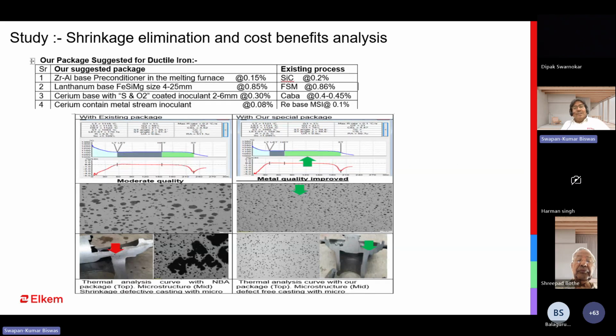This is also another study. On the left side, you can see that with the existing combination they are getting a lot of shrinkage. Then we recommended a high performing package. We replaced silicon carbide with an aluminum and zircon containing preconditioner and lanthanum based ferrosilicon magnesium. Instead of calcium barium inoculant, with lesser addition, it is a cerium containing inoculant, specially coated with sulfur and oxygen, with lower addition. Then this is the right side structure. You can see this casting photo with microstructure. That is the huge change.